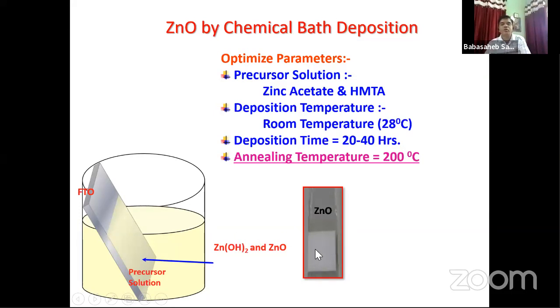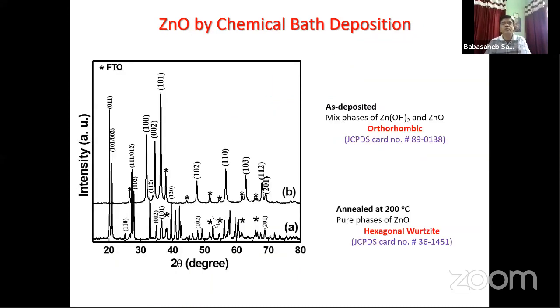And this is the photo image of the zinc oxide, which is white in color, deposited on the FTO coated glass substrate. The prior deposition of the seeded zinc oxide is there, which can act as a nucleation center for the growth of the zinc oxide. But for the dye-sensitized solar cell, you should have zinc oxide with a very high surface area. Before that, we did some characterization to see what type of zinc oxide it is, and we observed that it also has a hexagonal wurtzite structure.